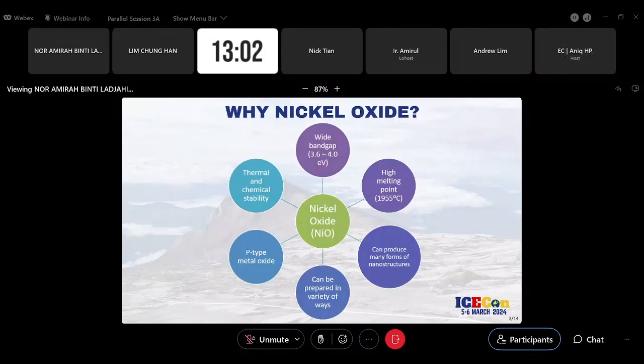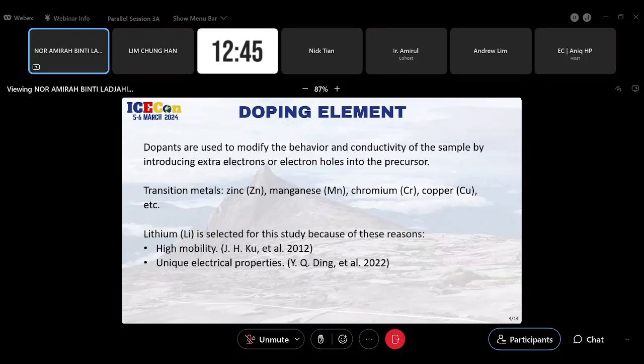So moving to the content of our work, we are choosing nickel oxide, a P-type metal oxide semiconductor, as a precursor due to its unique properties. As you can see here, there are 6 properties. For doping, we are using lithium. Why? Because previous research has proved that adding dopant element into precursor sample can modify the conductivity of the sample. Popular metal that often used by researcher like zinc, manganese, chromium, lithium and copper. We choose lithium because lithium has high mobility, which means they can easily move through the material and have unique electrical property, where it can donate electron easily, allowing it to alter the conductivity and electronic structure of the semiconductor.